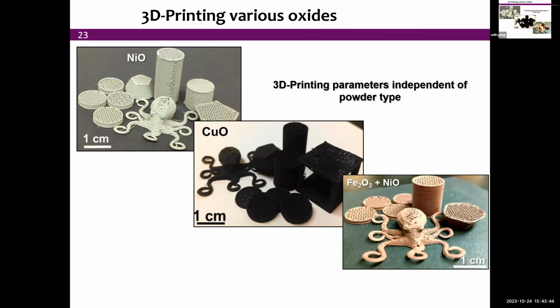So a few examples of various oxides. We have nickel oxide going to nickel, copper oxide that will go to copper, and of course, you can start mixing oxides. So iron and nickel oxide obviously will go to iron-nickel, which is kind of a prototypical steel, and here the additional issue is the interdiffusion. Once you reduce the oxide, you have pure iron, pure nickel. So not only do you want to sinter, you also want to interdiffuse to achieve a homogeneous alloy. So that gives us an extra lever. So in principle, it's pretty much any metallic composition for which the oxide can be reduced with hydrogen, which gives us at least a good 8 practical elements.